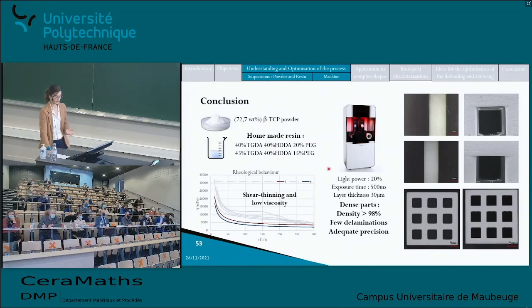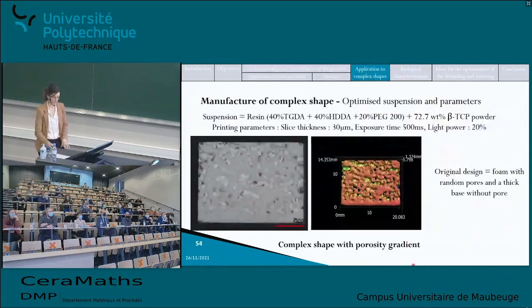And all of that enabled the printing of dense parts with density above 98%, with only a few delaminations and an adequate precision. So the next step was to adapt this optimized composition to complex shapes, because the goal is to print bone implants, and bones are not just rectangles. They have porosity gradients and they have different structures. So the original design chosen here was a foam with random pores and a thick base at the bottom without any pores.